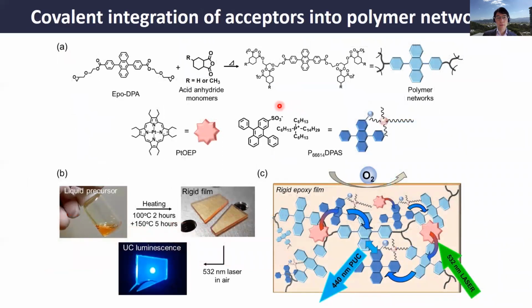Okay, then we recently have some more updates on this system. Here, in addition to this ionic liquid type of acceptor, we also incorporate the acceptor unit covalently in the epoxy network. So now we have two types of acceptor, one ionic liquid and one in the polymer network. Again, we use the same donor PtOEP, and we first make the liquid precursor, a mixture of all of them. By just heating at 100 degrees C and 150 degrees C, we obtain this rigid cured epoxy resin. By shining the green laser, again, we could observe nice blue upconverted emission in air.